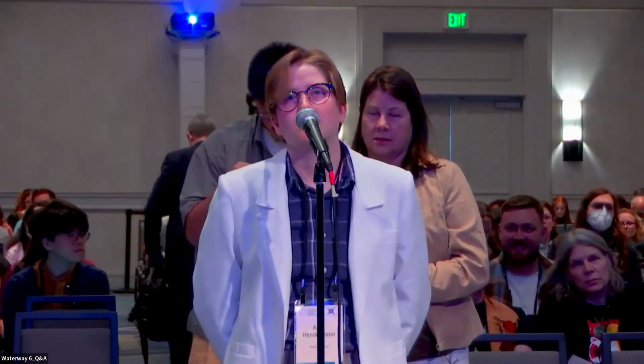100%. I think that's what really needs to be focused on when we're encouraging people to look for just the 2.5 and not the 2.3 and the 2.5, because other things can absorb in that area. It'll have to be compared with the carbonate spectra and the spectra of the mixtures that we're presenting, and then compared really carefully against other clays and sulfates. Luckily, a lot of things that absorb at 2.5 tend to be quite a bit broader, or these sort of shoulders, as I was describing, but it's definitely something to be treated with a lot of caution. I wouldn't necessarily recommend making a band depth map of the 2.5 all across Mars and then saying maybe these are all carbonate detections.